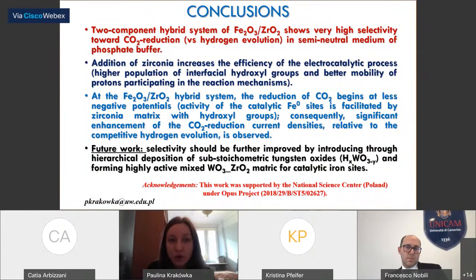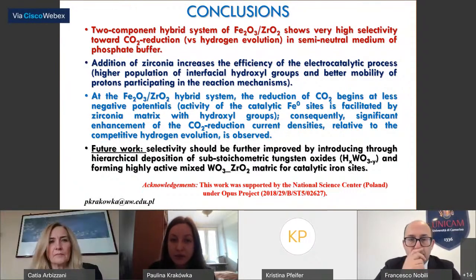To conclude, the two-component hybrid system of iron oxide zirconium shows very high selectivity towards CO2 reduction. Addition of zirconia increases the efficiency of the process. At the iron oxide zirconium hybrid system, the reduction of CO2 begins at less negative potentials, and consequently significant enhancement of the CO2 reduction current densities relative to the competitive hydrogen evolution is observed.